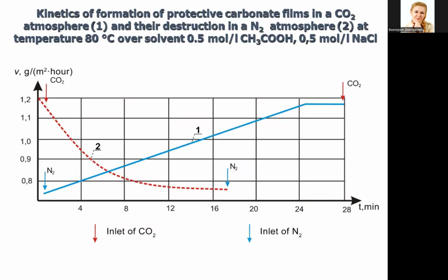Stabilization of the corrosion rate in the gas phase in the carbon dioxide atmosphere after nitrogen atmosphere occurs twice as fast as in a nitrogen atmosphere after carbon dioxide. From the given temperature and kinetic dependencies, it follows that acetic acid vapors increase carbon dioxide corrosion. However, the combined action of carbon dioxide and acetic acid causes less corrosion than acetic acid vapor.